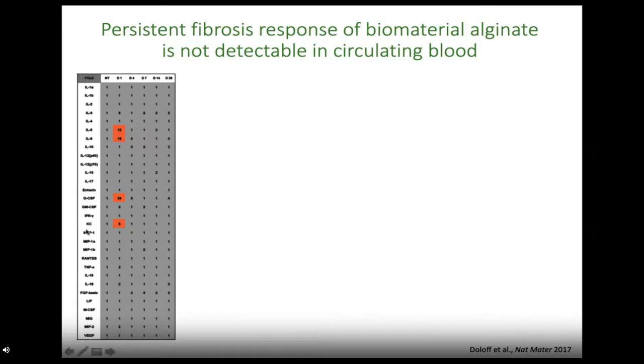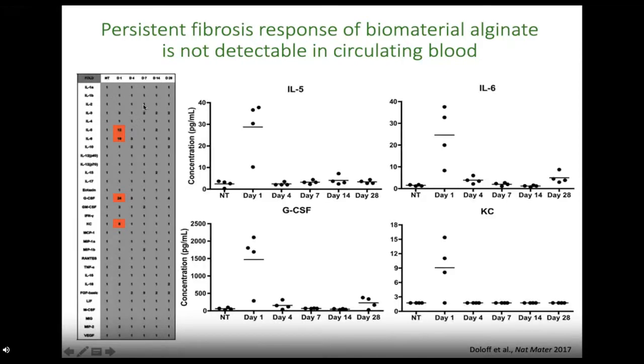Of approximately 30 factors, only four increased, and we only saw significant increases on day one following implantation. When we followed up with each of these molecules, they all went back to baseline within the next three to four days — indicating that rather than seeing a long-term buildup locally around the implant, we associated this instead with a day-zero surgery event which then dissipates over time.